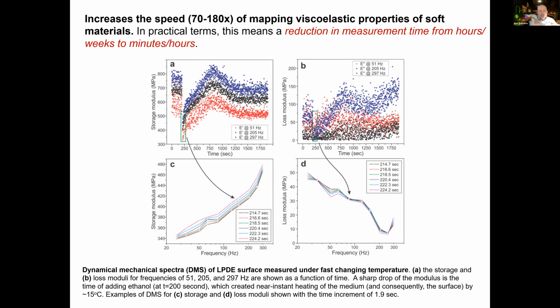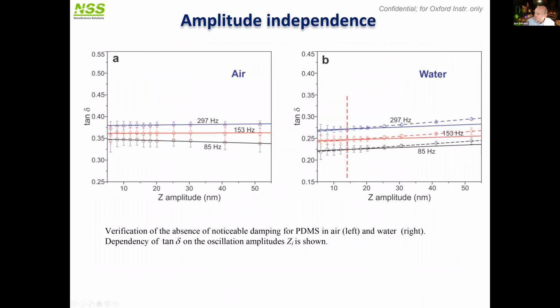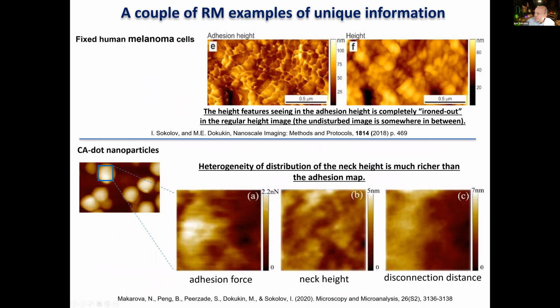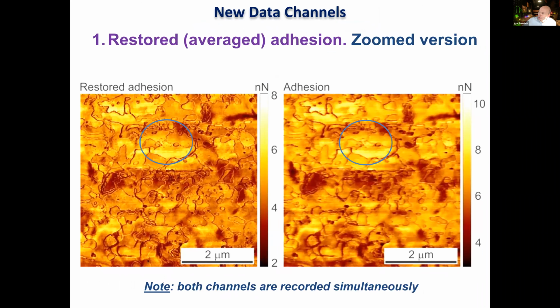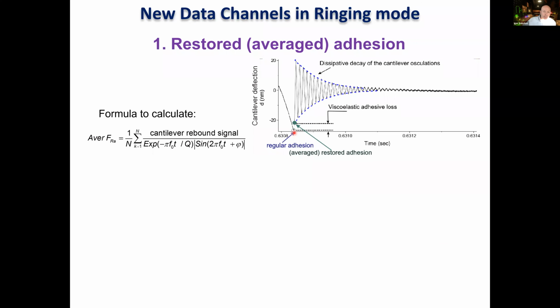And then when you pull it off, it's not a completely dried layer that sticks like a crust. It is still a relatively mobile and hydrated layer. So when we pull off, we can see those molecules. That's our explanation. Of course, we rarely see individual molecules clearly in the force curves, but we see them as an indication through energy losses. Remember when I showed the explanation at the beginning of ringing mode: when we do the projection, we never get exactly the same adhesion. That means only one thing, there is energy loss.